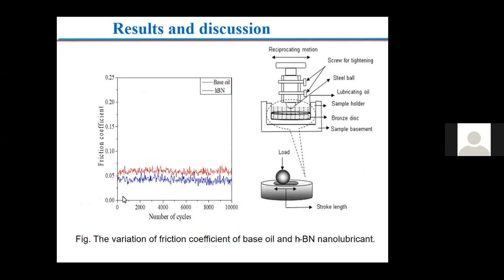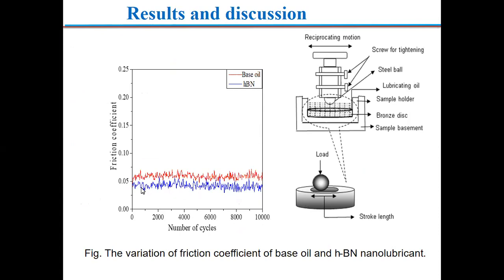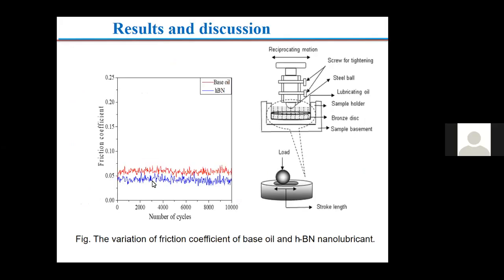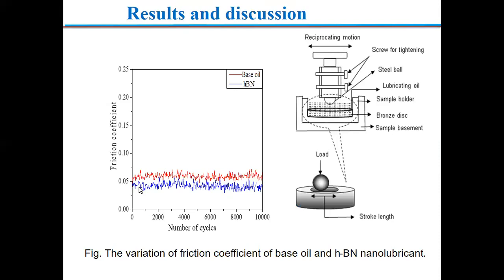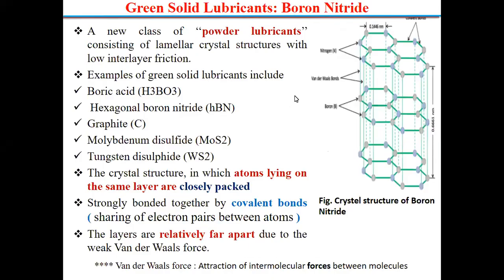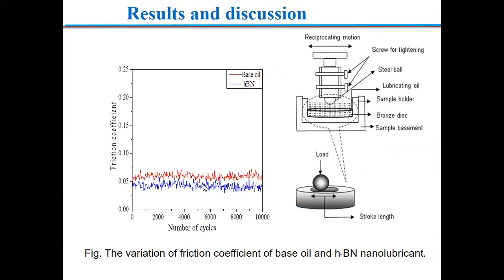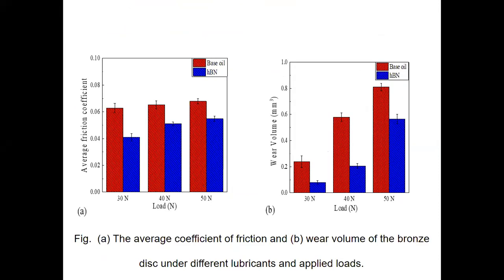Friction coefficient was plotted with respect to number of cycles. This friction coefficient is comparatively less when compared to base oil. You can see the reduction in friction coefficient over a number of cycles in this fashion. Because of this boron nitride, the friction has been reduced. Similarly, we have wear volume also. This is for one speed, and 3 load conditions were there. For all the load conditions, the average friction coefficient has been reduced. There is a reduction in friction coefficient with respect to increase in load, and wear volume also is reduced with respect to increase in loads.